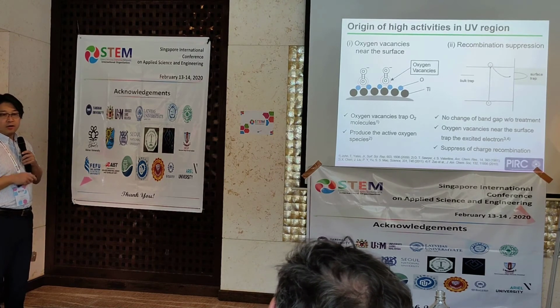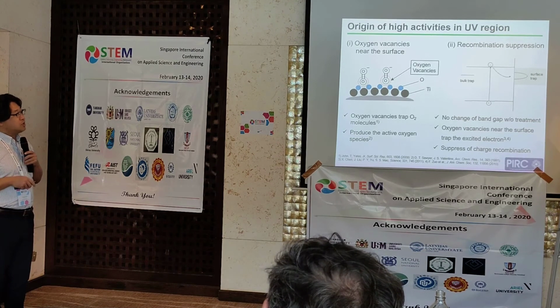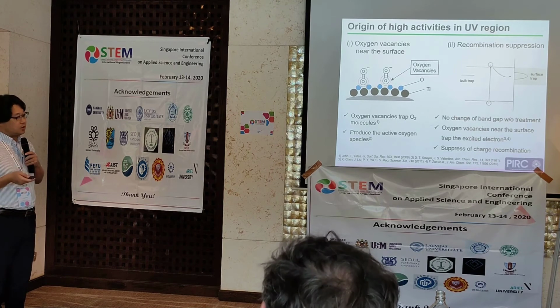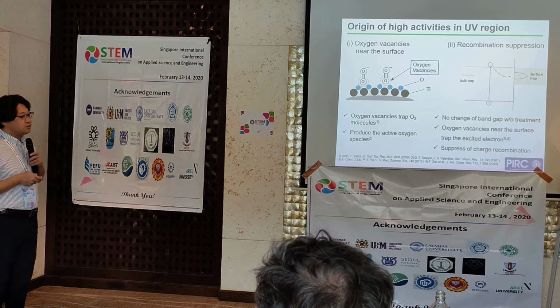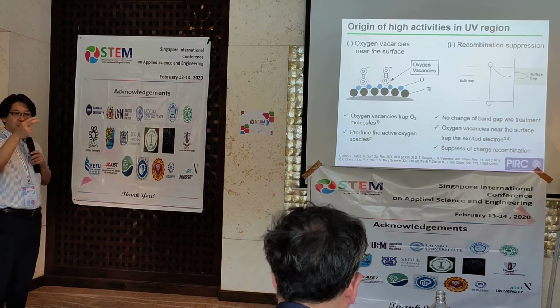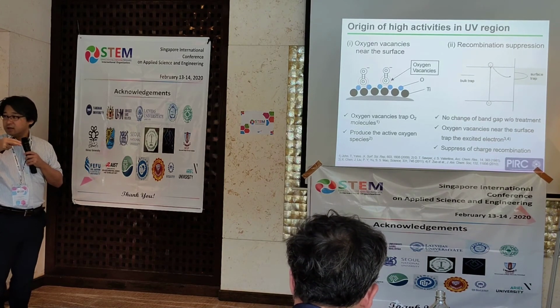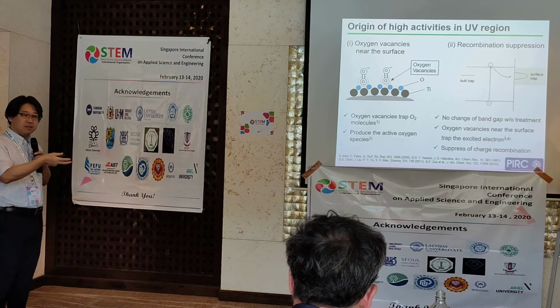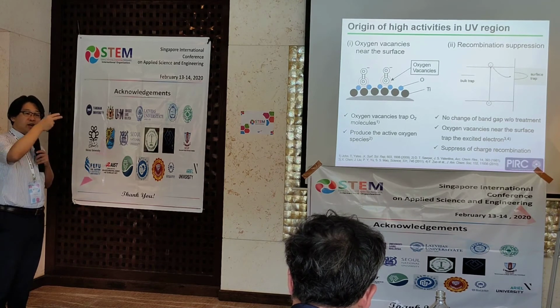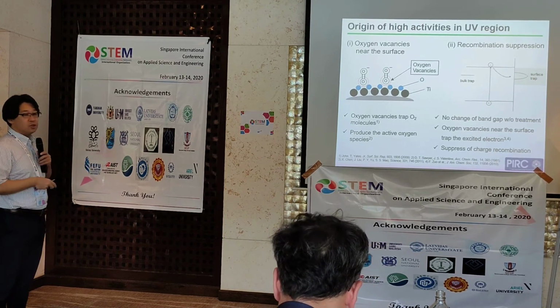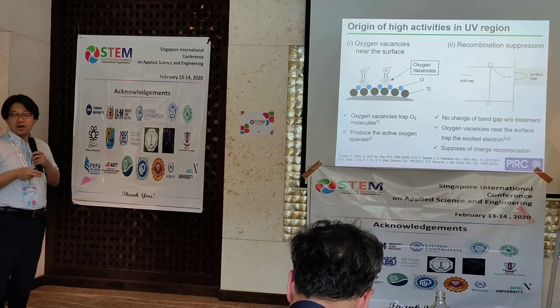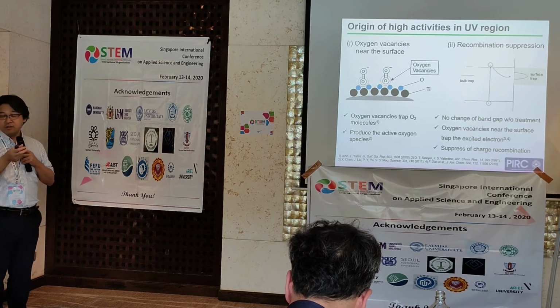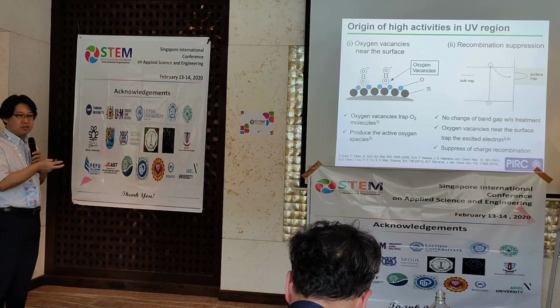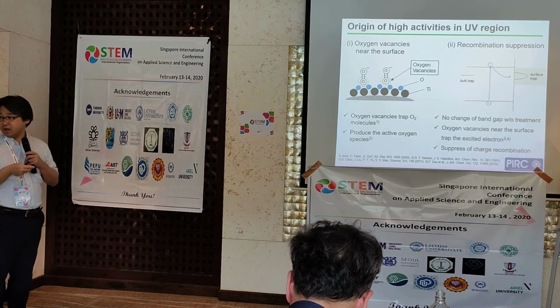So we considered why our sample shows this UV region activity. One is the oxygen vacancy near the surface of the sample. The oxygen vacancy traps the oxygen molecule from the atmosphere. Then light is irradiated. The excited electron couples with the oxygen molecule to produce active oxygen species. These active oxygen species decompose the chemical.